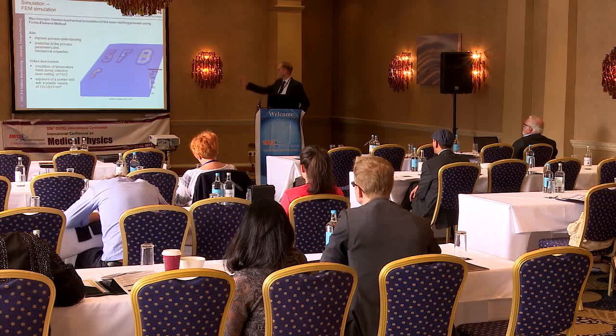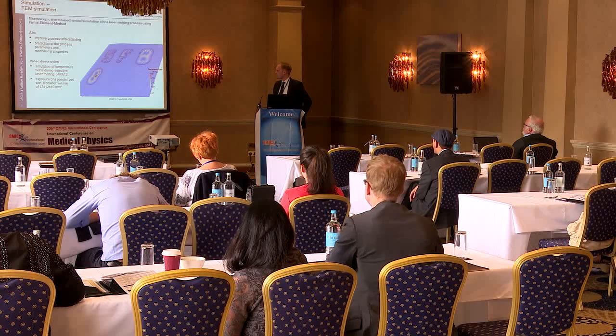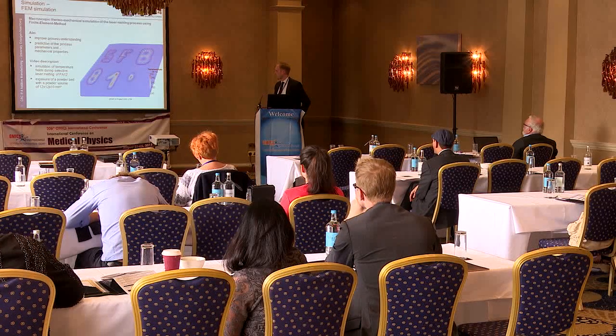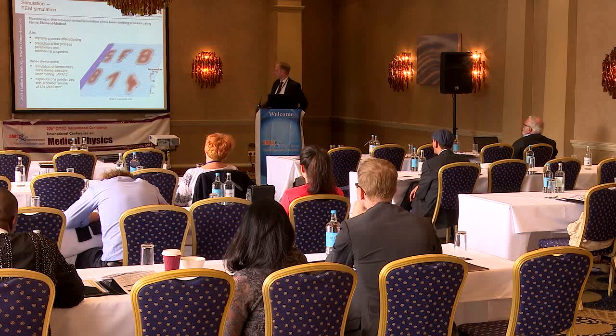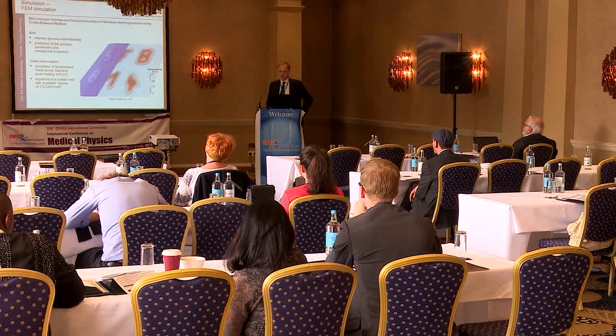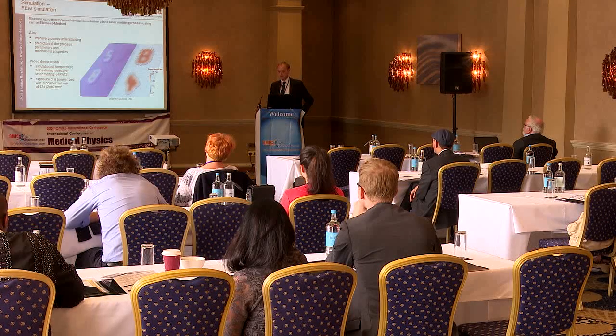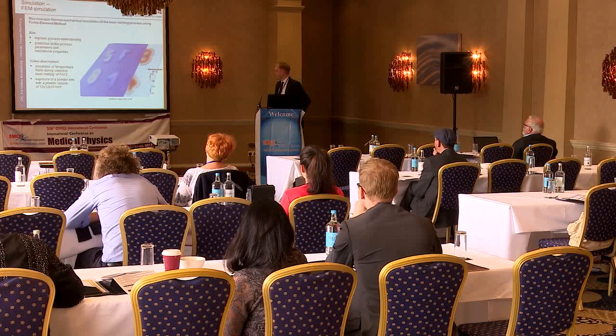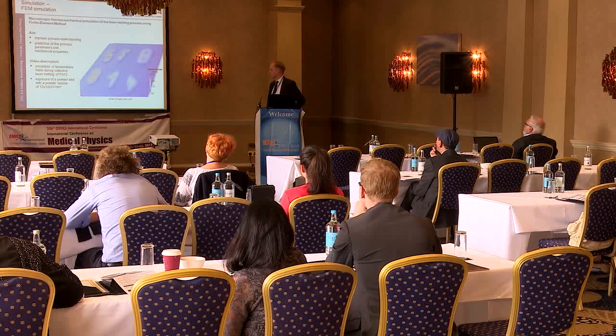And last but not least, we have this simulation of our temperature fields, which appear during the laser exposure. You can see this here. For a polymer material, the laser writes or exposes the geometry. And the red temperatures are the temperatures which are critical for our polymer. At this kind of temperature, you can get degradation effects. And you can also see how a new layer is applied and how the thermal interaction between the new and previously exposed layer appears.